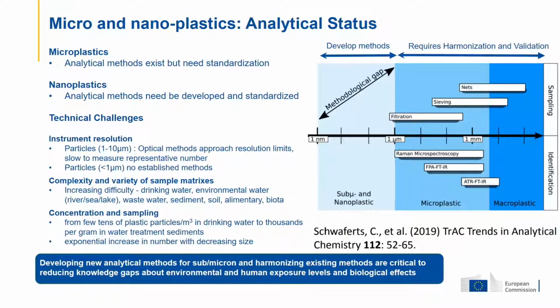Although the submicron range is not totally without methods, the approaches available are at early stages of development or require a combination of methodologies, in contrast to the micro-size range, where the dominant methods, micro-FTIR and micro-Raman, can both identify and enumerate the presence of microplastics.